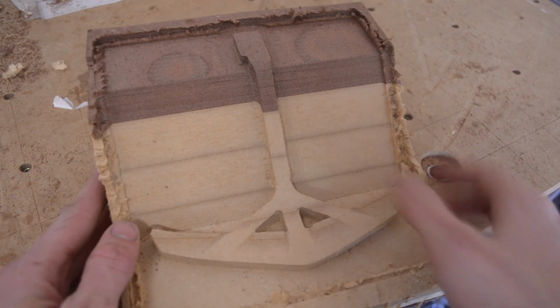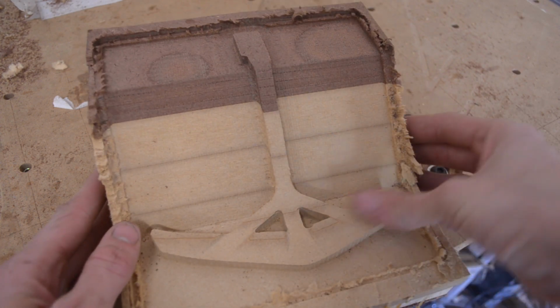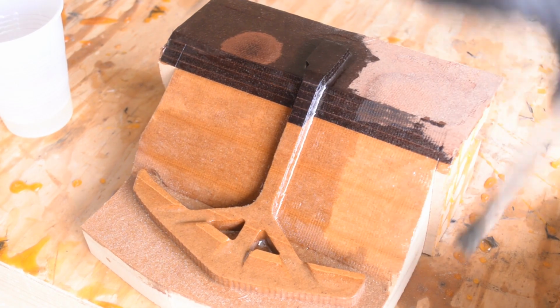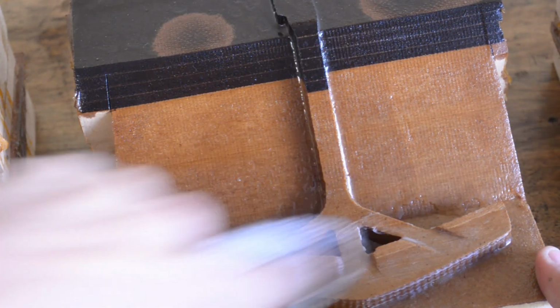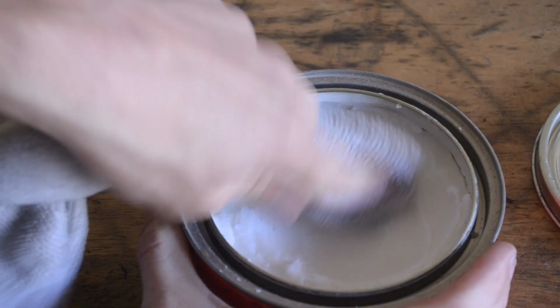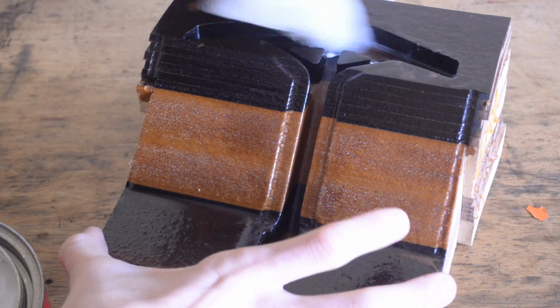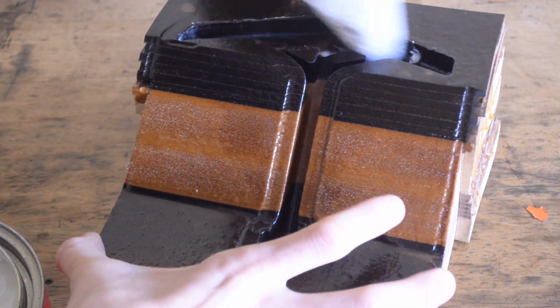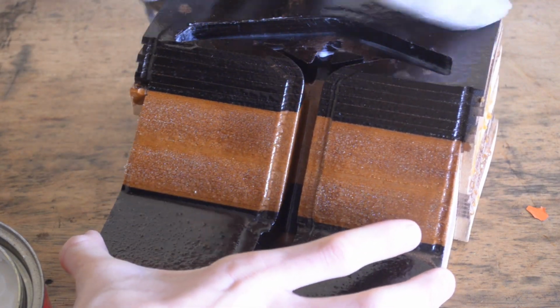And then we have to post-process these molds. So what we do first is we coat them in epoxy. And this provides a really hard surface finish. So when we go to actually lay up the paddle, the epoxy doesn't seep into the actual mold itself. Then we have to put on the mold release on all surfaces, and this really allows us to disbond it after the paddle is cured. So really important step, and be sure to do that. And now we can lay it up.